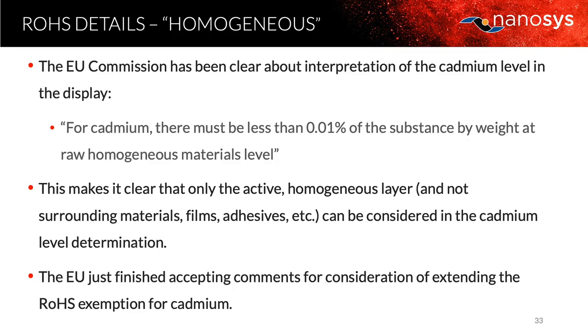This organization is also very clear about how to interpret 100 ppm of cadmium. I've heard different organizations talk about it differently, but they say it must be less than 0.01%, that is 100 ppm of the substance by weight at the raw homogeneous materials level. So if you make a film and you're laminating a bunch of things together, it doesn't mean you get to include all the films and so forth in that calculation. So it's a fairly rigorous requirement, and it's important to understand what life would be like in the absence of this exemption that's in place.